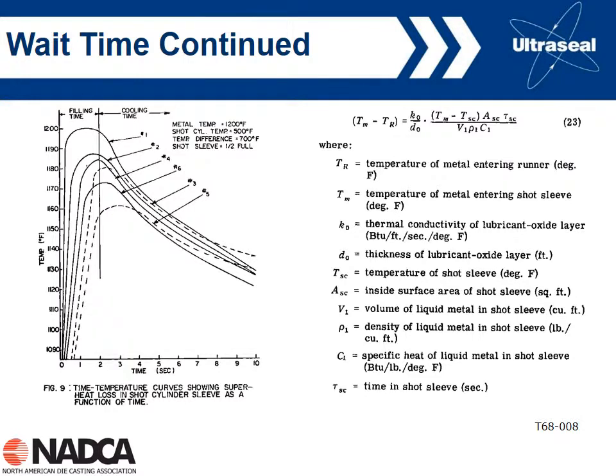This graph shows the temperature against time for the 6 different thermocouples that I showed in the previous graph. It shows that after a pretty short period of time, around 2 seconds or so for their experimental conditions, we start to get a dramatic loss of temperature in the shot sleeve. So if we wait too long, and too long is not a very long time, we get a lot of pre-solidification in the sleeve. Maybe we have to go faster to prevent non-fills. We talked about this earlier, that going very fast can produce problems. The bottom line is that these data show longer wait times are bad, and they're going to increase the amount of porosity in our castings.